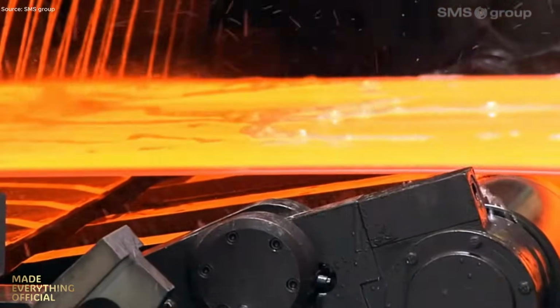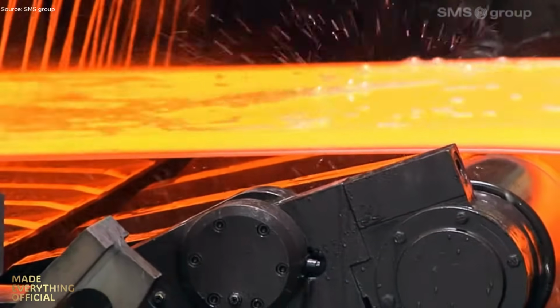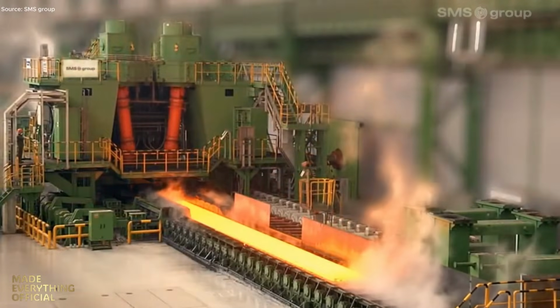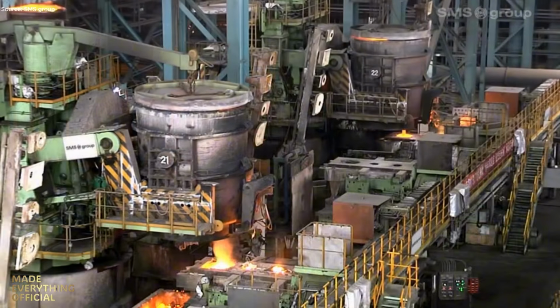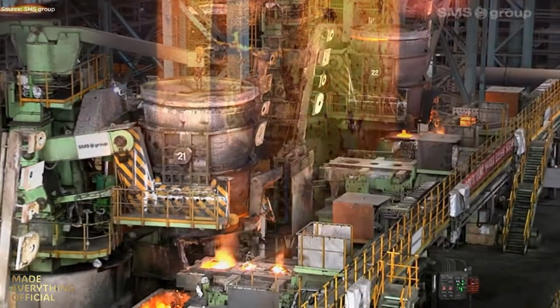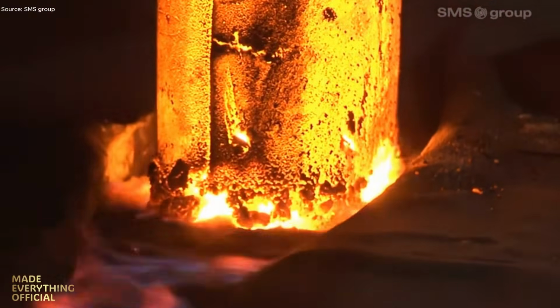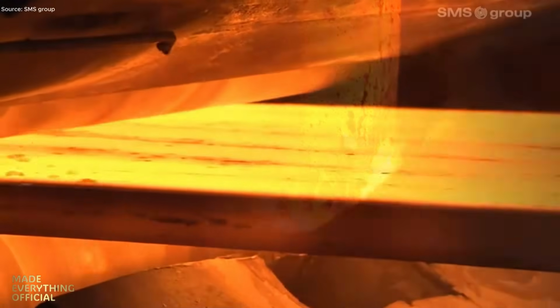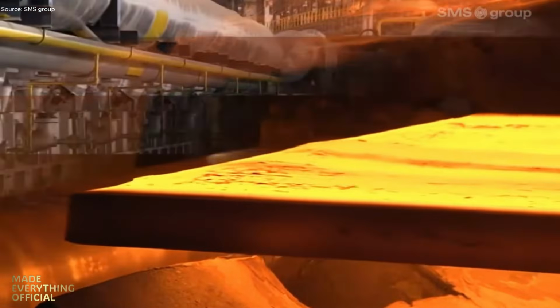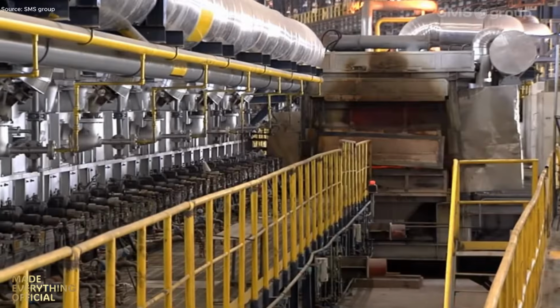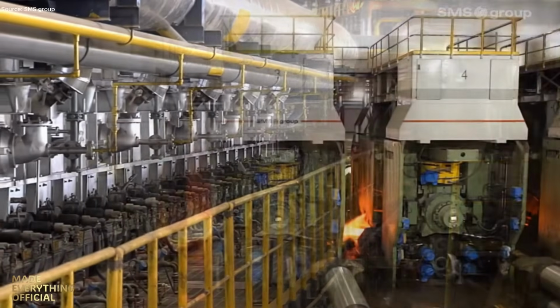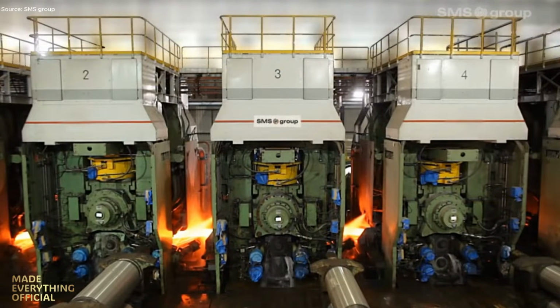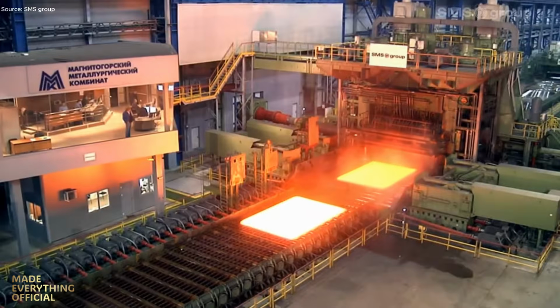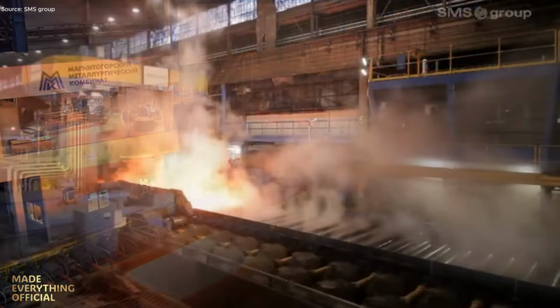Massive rolls apply pressure in successive stands, reducing the slab's thickness with each pass. The metal flows like liquid under controlled force, stretching and widening into long, perfect strips. Between stands, water sprays cool the surface while maintaining the steel's core temperature for accurate shaping. Sensors and automation synchronize every roll, every millisecond. The system constantly measures temperature, thickness, and flatness, ensuring consistency across the entire width of the strip.